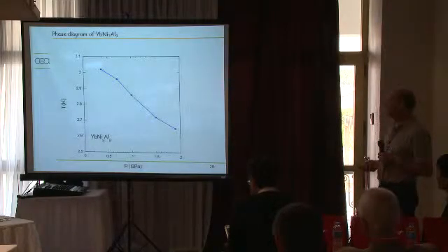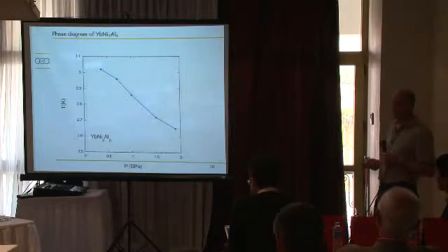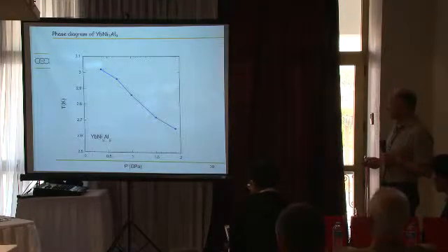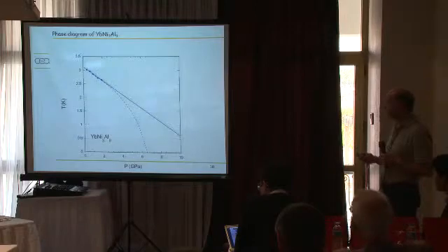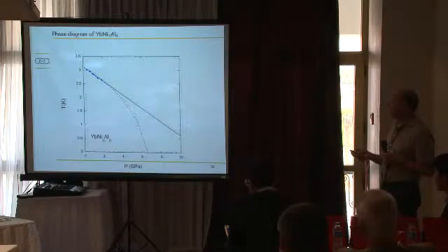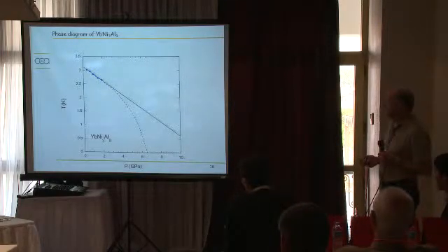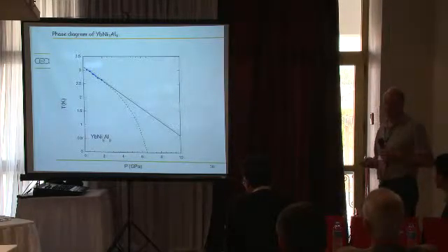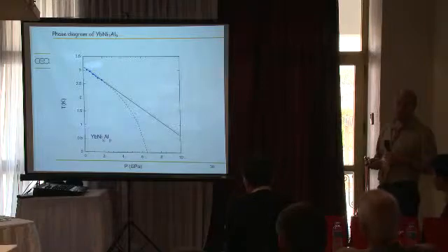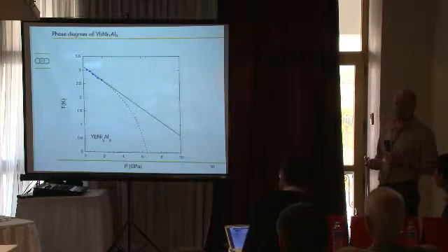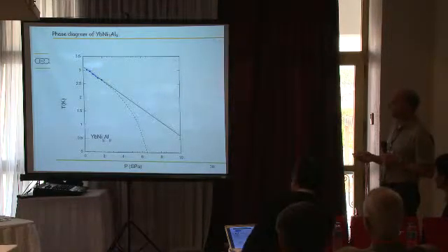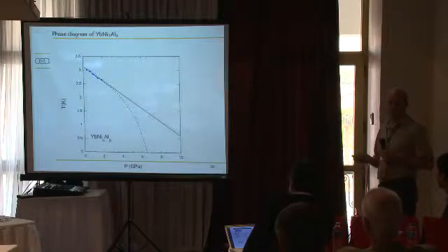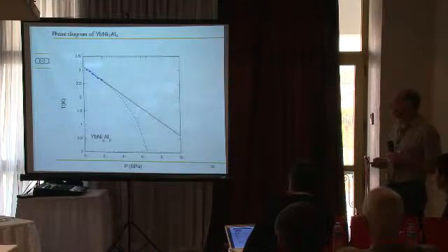And if we follow the ordering temperature, we see that this indeed decreases with pressure. If we take the first point, if we extrapolated a linear fit, we thought we might be able to reach and study a critical point at a bit above 10 GPa, maybe even lower, because you don't expect really from critical behavior a linear, but something decreasing stronger.